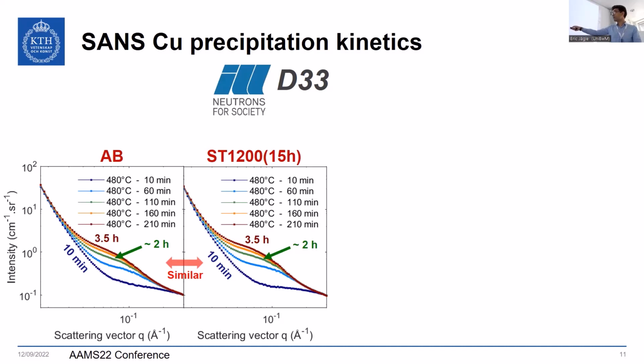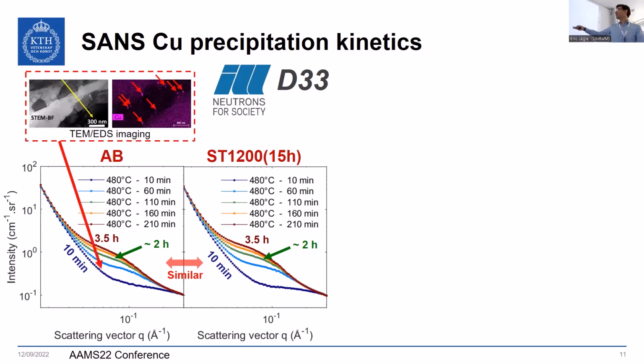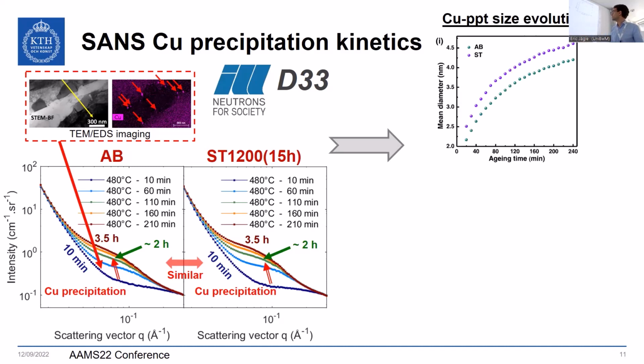Right? And you see that finally both curves are relatively similar, which means that the precipitation is relatively similar. The starting point has very few copper precipitates, which also explains why the hardness is so low. And we still have a few precipitates. We can model them here, actually, even if it's not obvious by eye, and we can also see it by TEM. And here, with time, you see the copper precipitation increasing, with this precipitate contribution increasing.